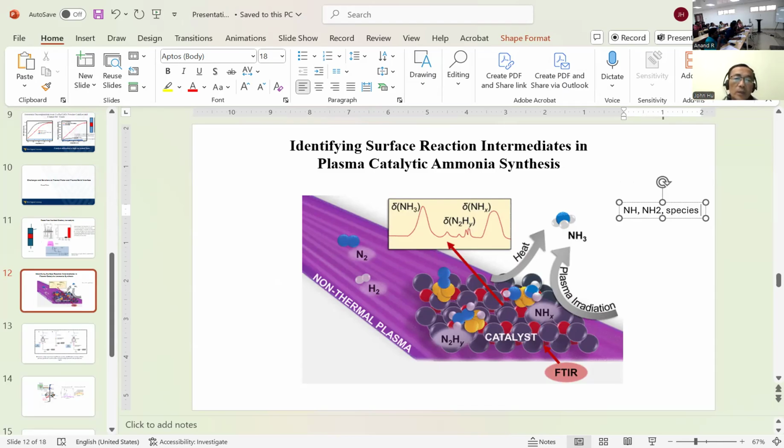They can really see what's happening. They have the delta, the NHx and N2H, whatever you name. This IR can see the evolution of the formation mechanism from N2 dissociation. N2 has to dissociate in order to combine with H. Is that right? This in situ IR is really powerful.